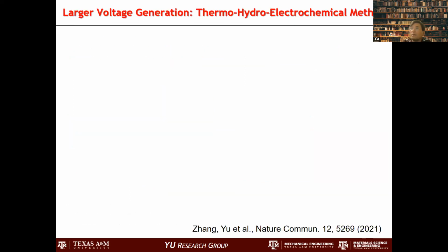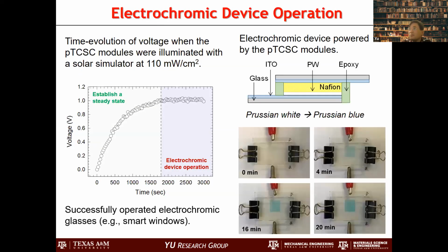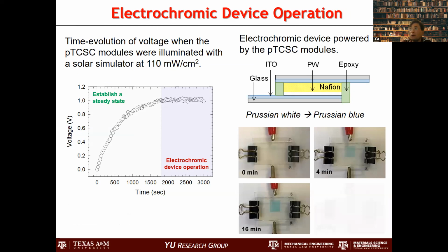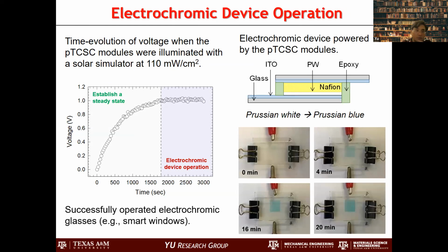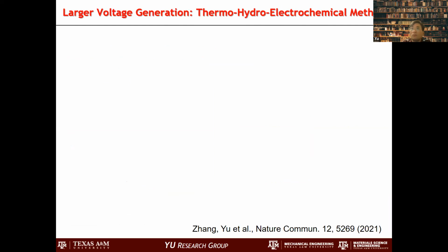Okay. But this is 2 volts, while the thermal power, as you saw, is only 10 millivolt per Kelvin. We're not satisfied. 10 millivolt per Kelvin is still too small. So we want to have an even larger one, and then we need an additional effect. What we did at that time is, we used a thermal hydroelectrochemical method together. So we combine the effects to make a better device with a larger voltage generation. That's what we have done.